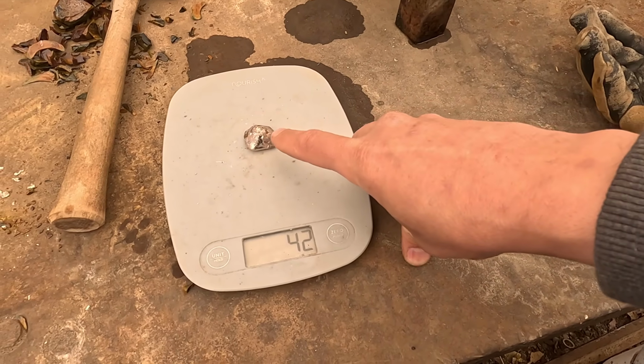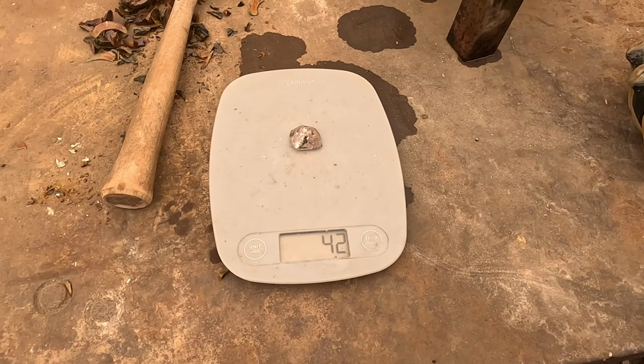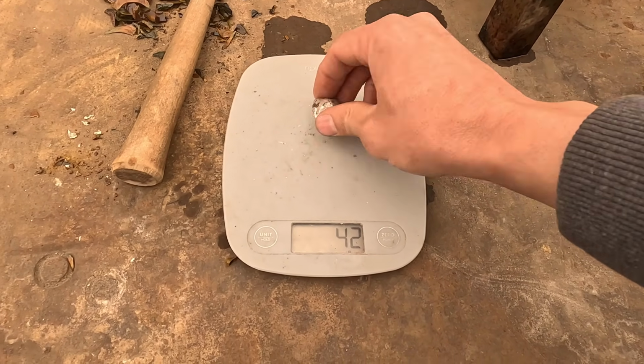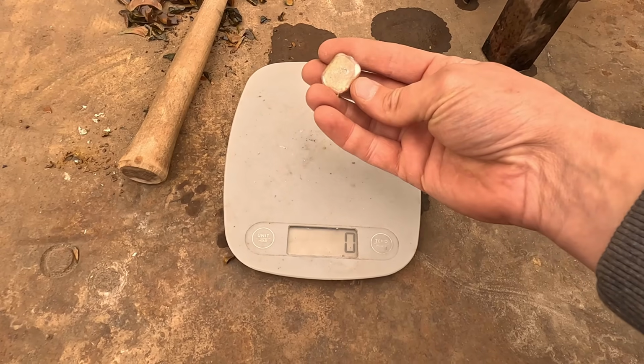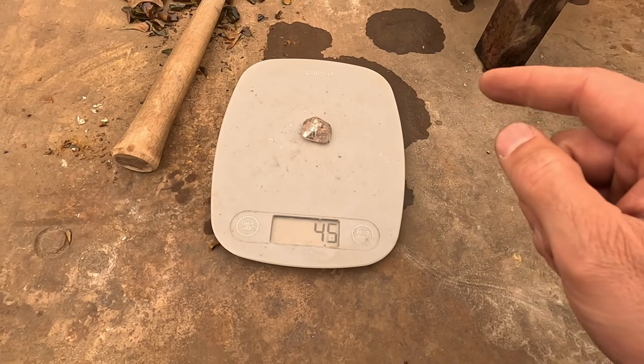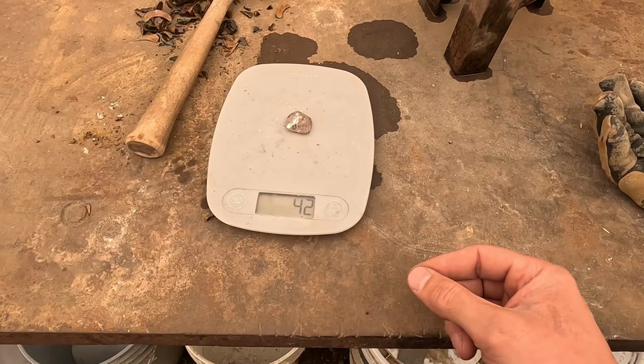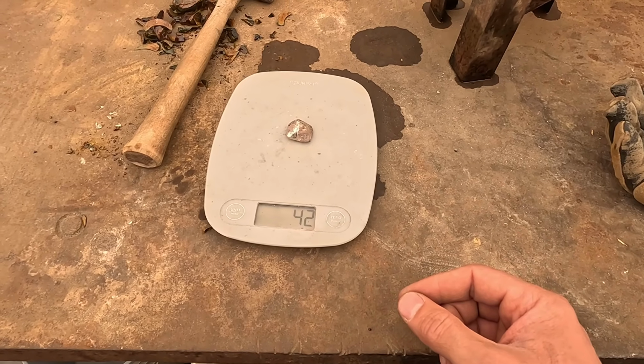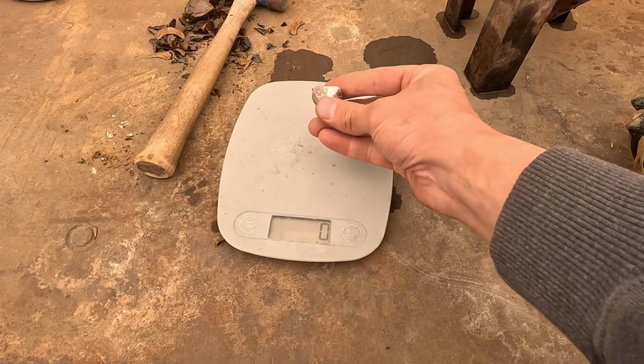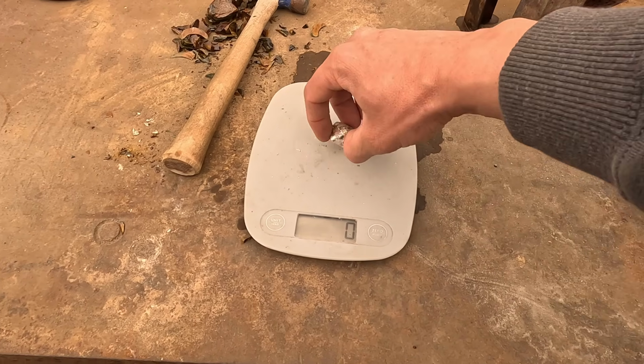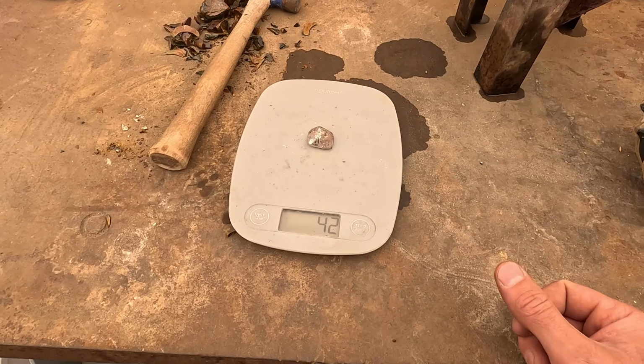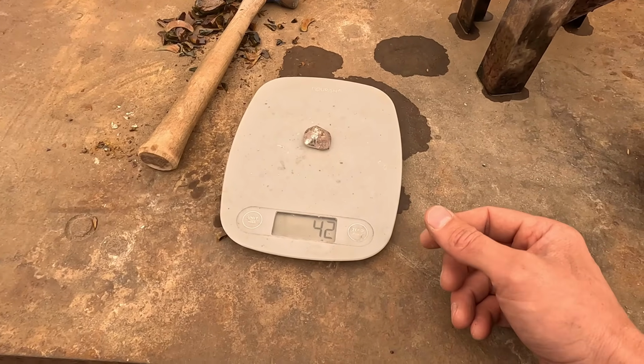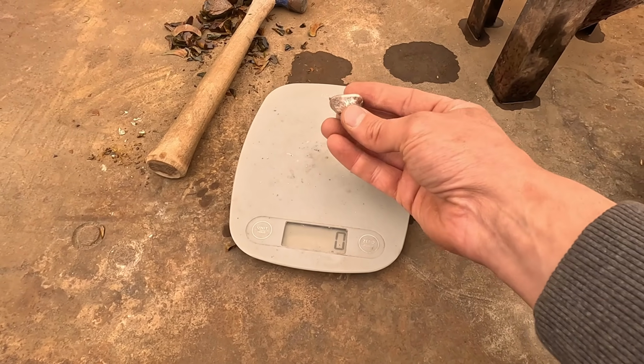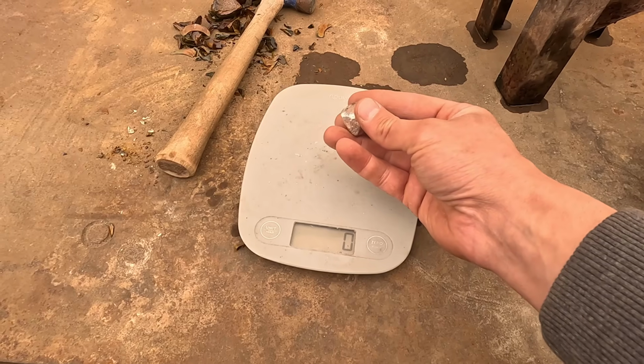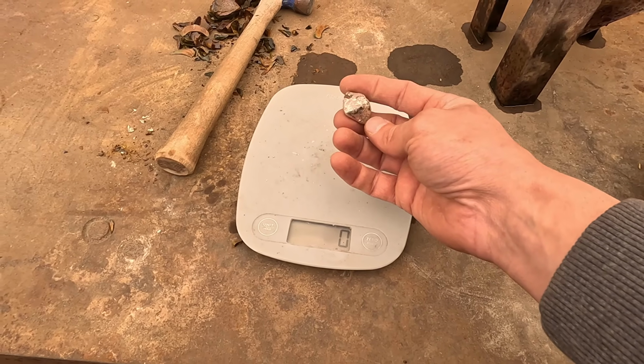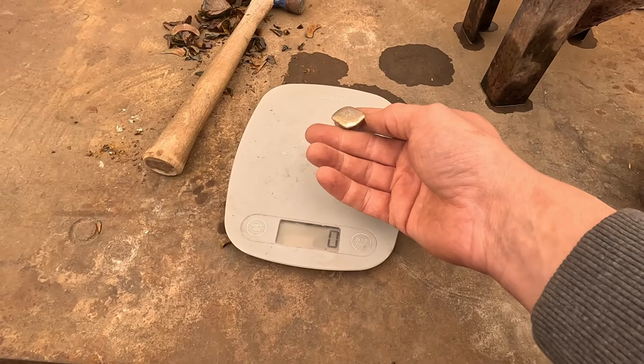If everything ran to completion, that means we have 30 grams of bismuth in there, some copper, and then whatever precious metals we have. So we could probably use a little more bismuth oxide or a little more oxidizer, but I'm really, really happy with that. We started with 50 grams. I added 30 grams of bismuth oxide, which would reduce to bismuth. And we got 42. I'm gonna try and throw that right in the cupel, I think. Is that what I wanna do? I think so. Let me think about that for a minute, but I'm really, really happy with that.